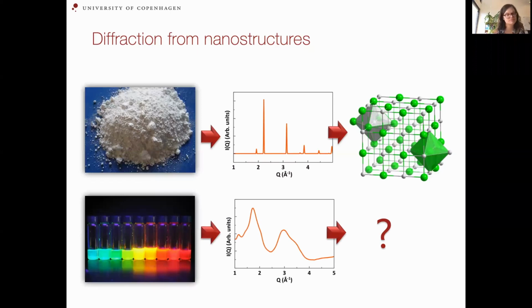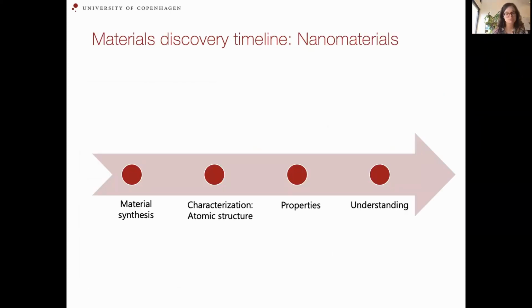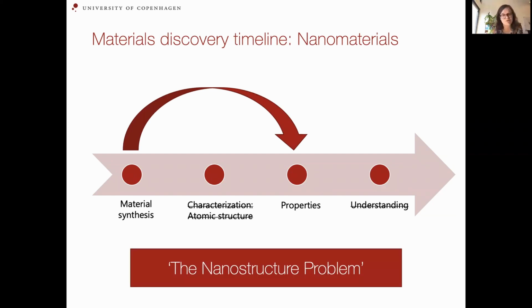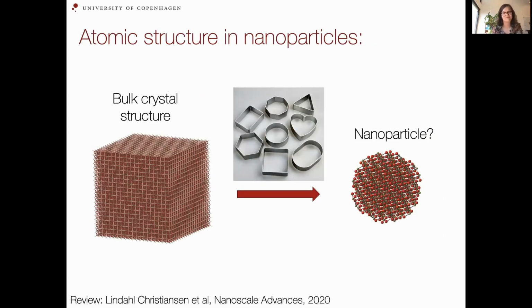And that's what we're interested in. We call it the nanostructure problem: if we cannot characterize atomic structure, then we can do material synthesis and we can test properties, but obtaining this understanding, which is needed for the next step, is a problem. And I'll show you some examples of how we solve it, because right now, what is basically done is to assume that the structure of a nanoparticle is the same as the bulk crystal structure, but that we just cut it out of the material.